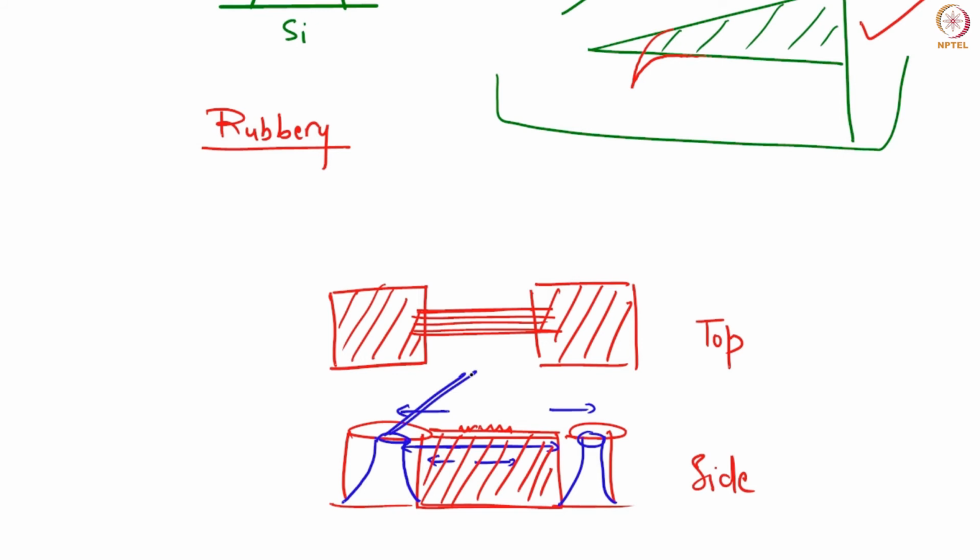So let's say this pillar is connected to another pillar here, and this pillar in another direction is connected to something. So basically, during the pyrolytic shrinkage, this pillar will be pulled in this direction, the other one will be pulled in this direction. In that case, your wall will be twisted. You will get something like this when you get the top view afterwards, after the pyrolysis, and then you have your pillars.